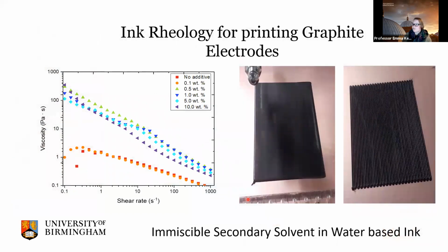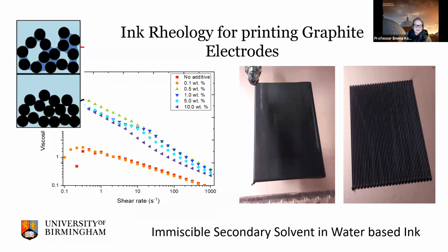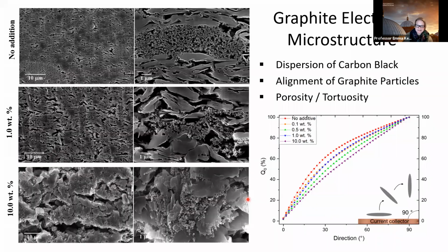So yes, we didn't calender it, and I can tell you why we didn't. Well, we did calender some and we didn't calender some of the others. What we were looking at was to see if we could change the morphology and the alignment by adding this secondary solvent, and we could. The problem with calendering is that, as I think this is what Jack is alluding to, you squash it and things align back together again.